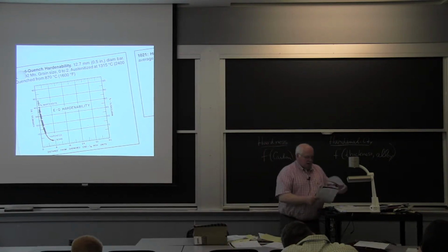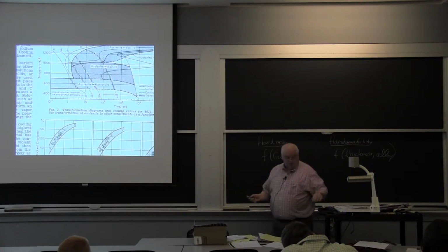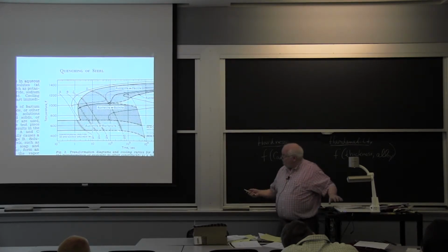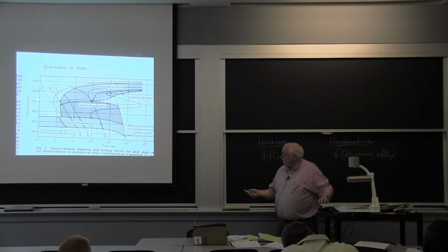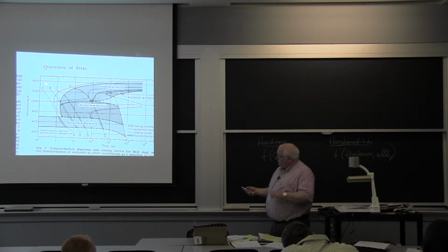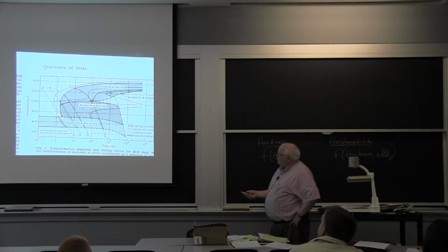Okay. So we have curves, and there are whole books with these types of curves, which are called continuous cooling transformation diagrams. So if I heat a steel up to, this would be Fahrenheit, 1400 degrees Fahrenheit, or actually I heat it up to about 1600 or 1700, and I quench it in water. This is time on a log scale, so this is 1 second. I have to quench that and cool it down within less than a second.